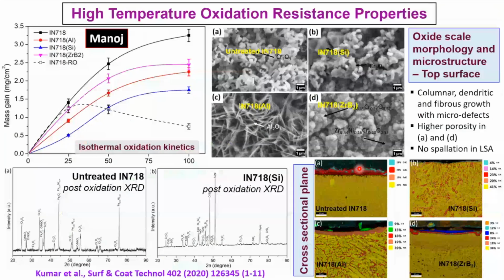When you look at these oxidation kinetics curves, the mass gain as a function of time, you realize that this bottom curve, the blue curve, is Inconel 718 surface alloyed with silicon. And that makes so much of a difference compared to the as-received Inconel 718, which undergoes oxidation at a much higher rate compared to this surface alloyed sample.